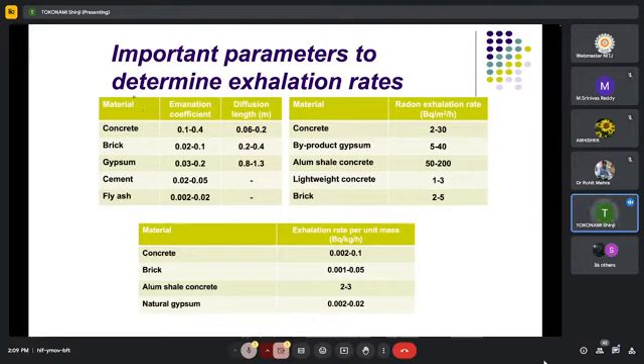This table shows different materials and emanation coefficient and diffusion length. Concrete, 0.1 to 0.4, the emanation coefficient, 0.06 to 0.2 as diffusion length. Brick, 0.02 to 0.1 emanation coefficient, 0.2 to 0.4. Gypsum 0.03 to 0.2, 0.8 to 1.3 as diffusion length.